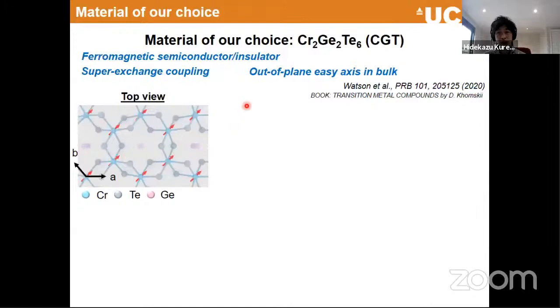The material of choice for us for this particular work is chromium germanium telluride. I will call it CGT from now on. This is a ferromagnetic semiconductor or insulator. It's a relatively narrow gap semiconductor, so it's probably right to say semiconductor. The exchange coupling is mediated by the superexchange regime. Also I want to highlight that it has an out-of-plane easy axis in the bulk or undoped regime. This is the top view of it, and you can see that the light blue balls represent the chromium ions, and they form a honeycomb lattice.